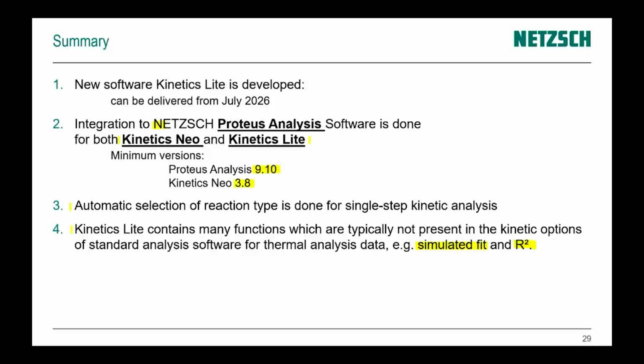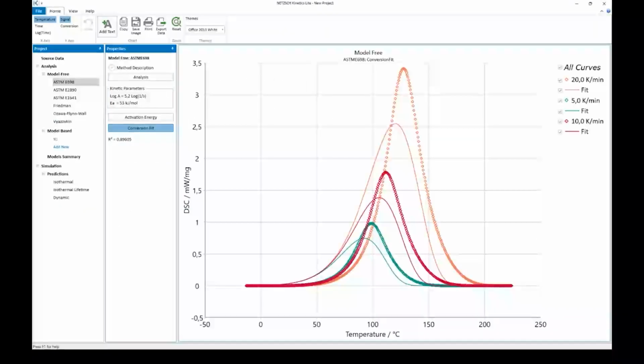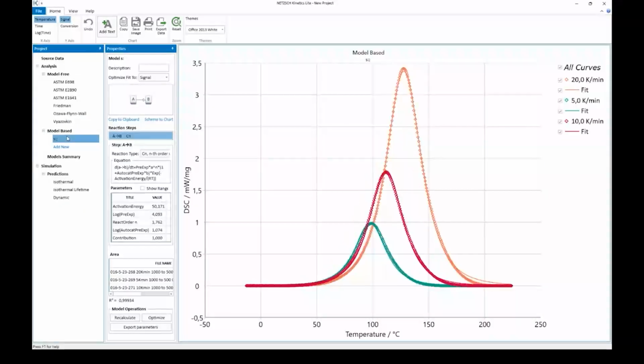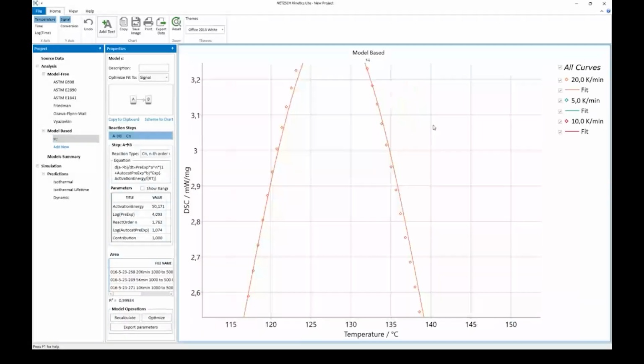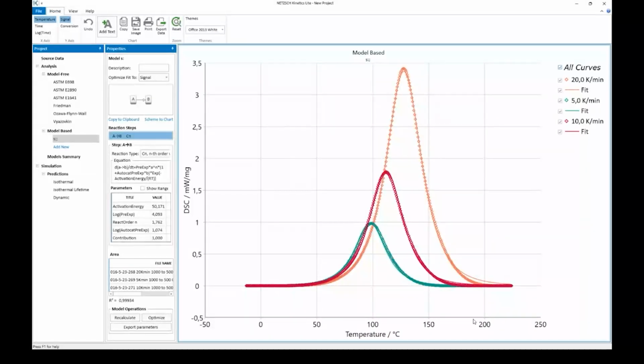So I will go back to our curves. So here we are inside. And we have here, firstly, our experimental data. Here is experimental data, and here is our fit. And this fit is calculated from activation energy and pre-exponential factor, and reaction order, and so on. So for this temperature program, the software tries to find activation energy and all other parameters, including pre-exponent, in order to have a good fit for all experimental data which are measured at different experimental conditions.